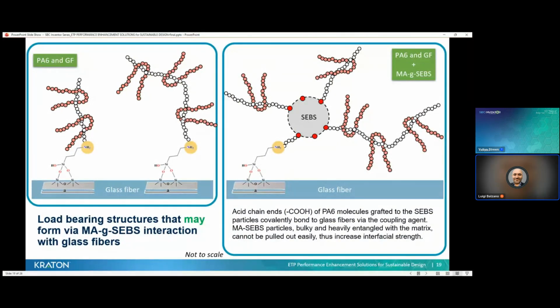Tensile properties of a composite are critically dependent on the bonding between the polymer and the filler, glass fiber in this case. For this reason, glass fiber producers introduce a coupling agent in their products, a low molecular weight compound that binds chemically to the glass surface on one side and it reacts with the polymer on the other side. Specifically, in the case of polyamide, the reaction is between the coupling agent and the acidic end groups of the polymer.